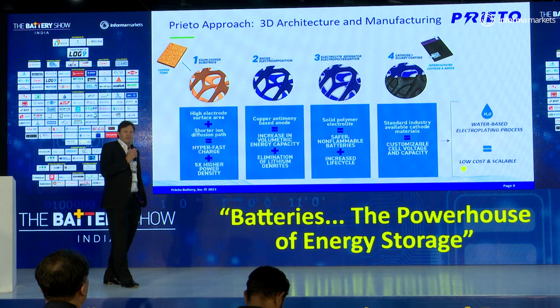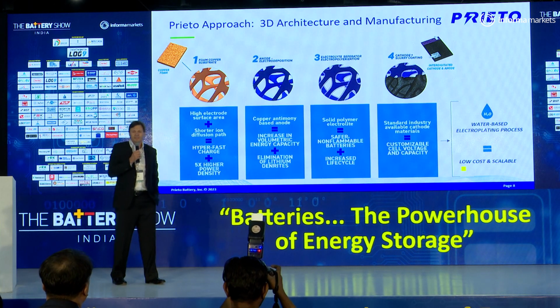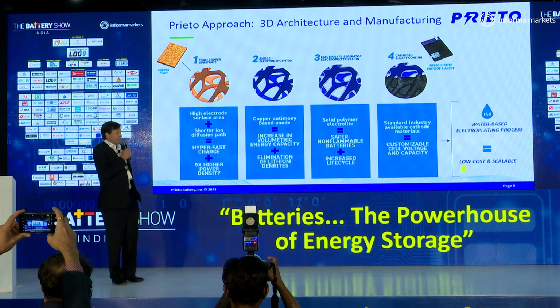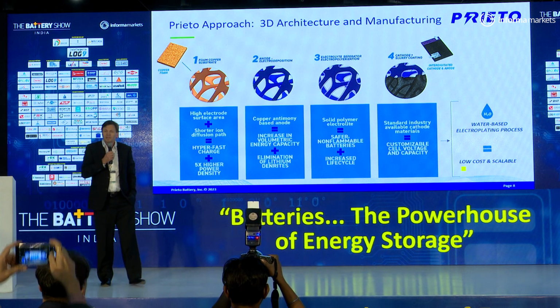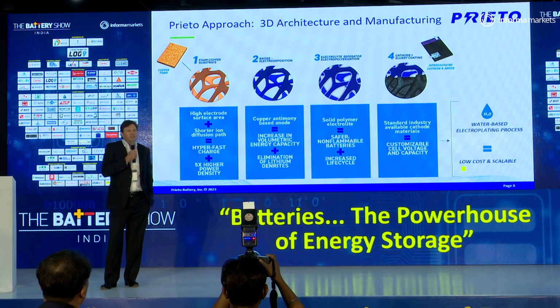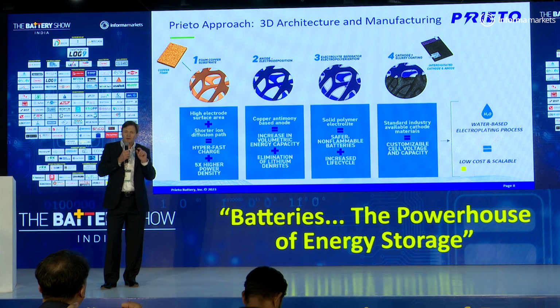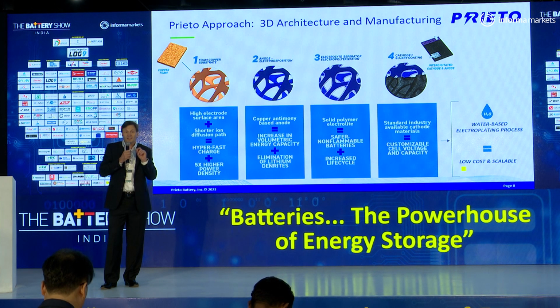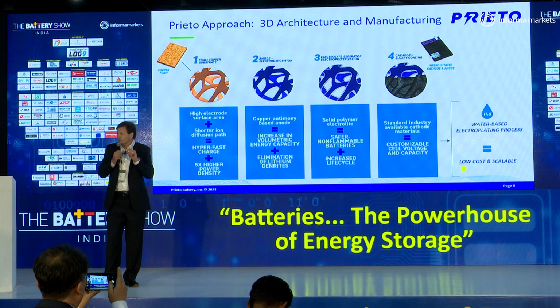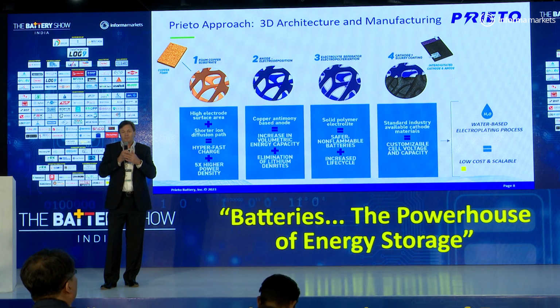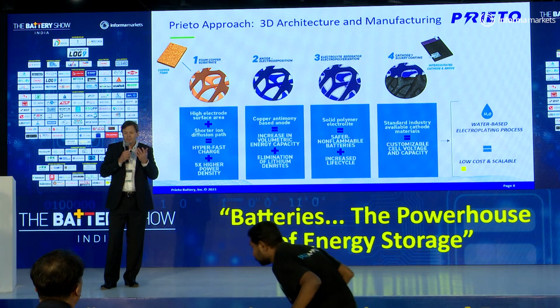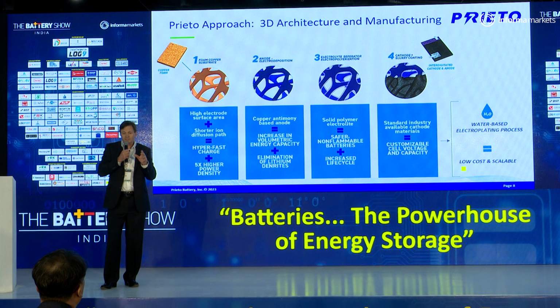This is sometimes a better way to look at it, how we actually put this together. We start with the copper foam on the upper left-hand side, and we electroplate our anode on top of that, which creates a very thin microlayer anode. Then we do the same thing electrically with our polymer separator, which is our electrolyte and separator. Again, very, very thin. Then we coat that with our cathode, and then we attach a current collector to it. So what you end up with is a lot of surface area around each individual strand. You get a lot of energy density, so a lot of materials in there, but the layers are so thin, you get super fast charging.